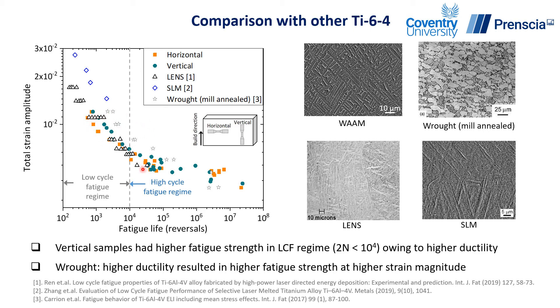When we compare our data with the literature, we can see that WAAM Ti-64 shows marginally lower fatigue performance than the wrought mill-annealed material. This is mainly due to the higher ductility associated with the wrought microstructure, which consists of a bimodal microstructure. However, when comparing WAAM Ti-64 properties with laser engineered net shaping, both AM processes show similar fatigue performance. On the other hand, SLM shows slightly higher fatigue performance due to the martensitic microstructure, which has a higher yield strength in these SLM materials.